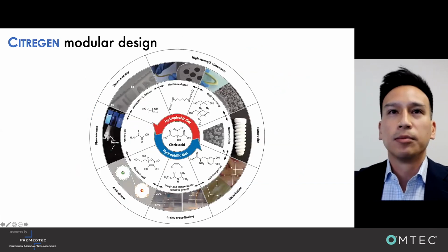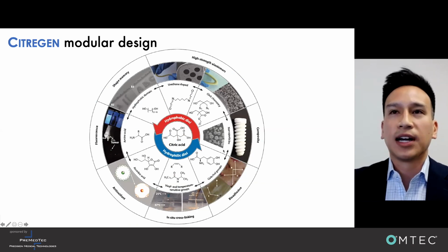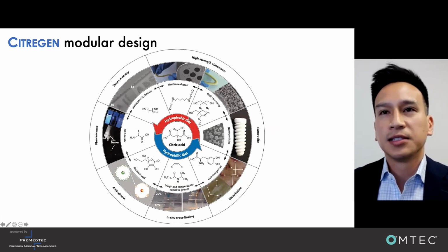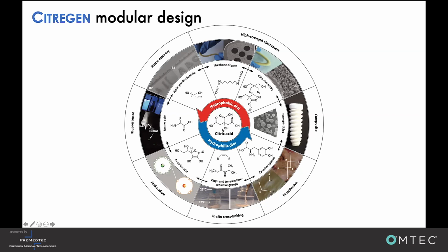I mentioned earlier the modular design of Citregen and why it's a platform material. This is a busy slide, but you can see that it all starts with the citric acid molecule. We then select hydrophobic or hydrophilic diols to control the degradation rate. And because of the unique bulk chemistry of the citric acid molecule, we're able to attach many different molecules to exhibit different properties.